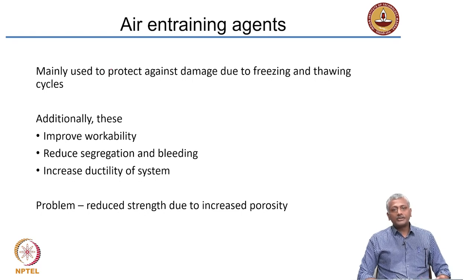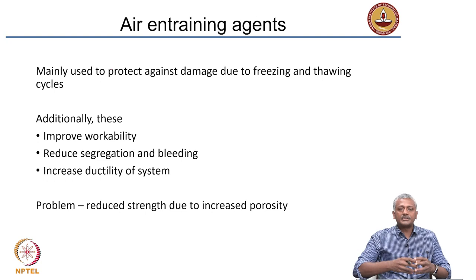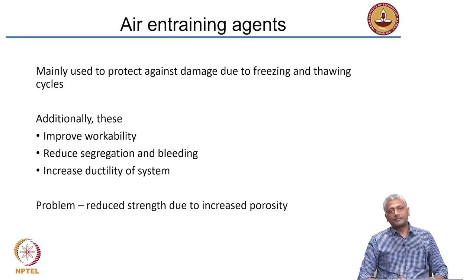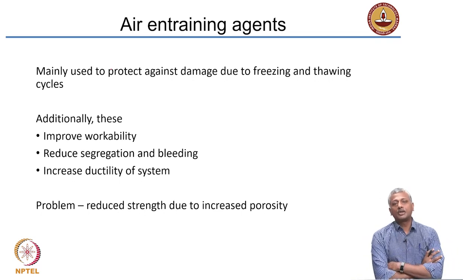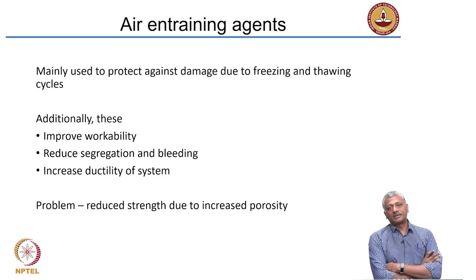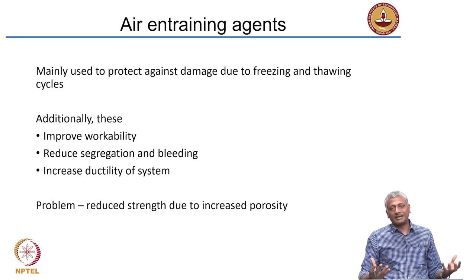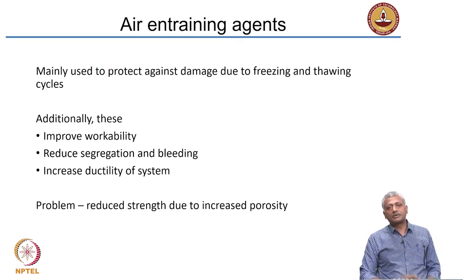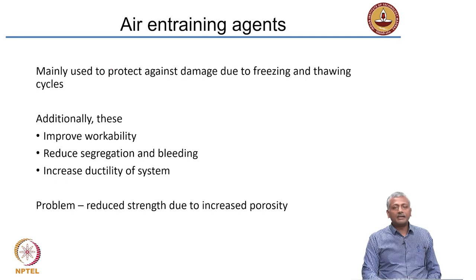In very cold areas, temperature fluctuations can cause the water inside concrete to freeze and then thaw. When water transforms to ice, it leads to an expansion in volume — an anomalous behavior. This expansion leads to stresses in the concrete causing cracking. In such cases, we put very small air bubbles in the concrete using air entraining agents, which create small air bubbles that provide a space for the water to convert to ice and expand, reducing stress and cracking. Freeze-thaw is a major problem in certain parts of the world and that is where air entraining agents can help.